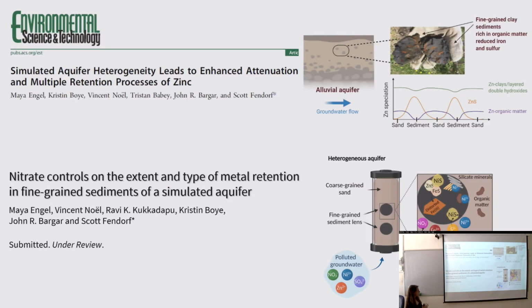So to summarise this theme here, I think that the most important finding is that the presence of these fine-grained lenses really does influence the retention of heavy metals and therefore the resulting groundwater quality. Now, even if the mass contribution of the lenses is small, their influence can be substantial, so they must be considered when we evaluate groundwater quality. Moreover, we have seen that the presence of redox-active species such as nitrate can further influence the accumulation of metals and also the form in which those metals are being retained.